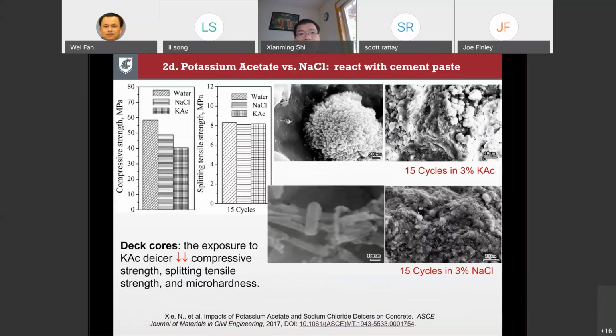Now, there are two interesting recent studies I want to share with you. One of them is this supposedly environmentally friendly deicer, potassium acetate, which is at least 10 times more expensive than sodium chloride, actually 20 times more expensive. It's typically used on airfield applications and also for highway departments, usually for fixed anti-icing, fixed automated spray technology on bridge decks. But we took some bridge deck cores and we found this deicer also posed a significant risk to the concrete, especially compromising its compressive strength, splitting tensile strength, and micro hardness.